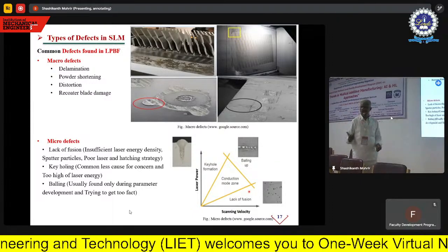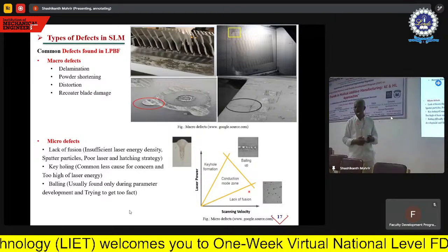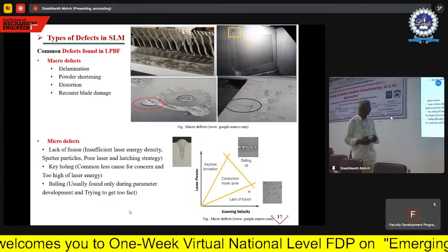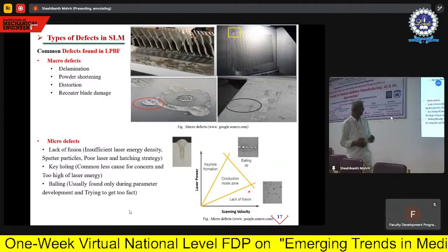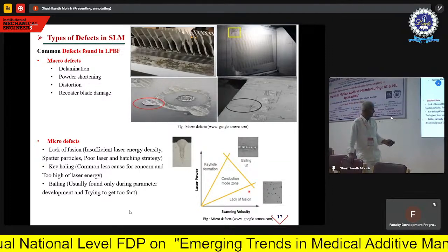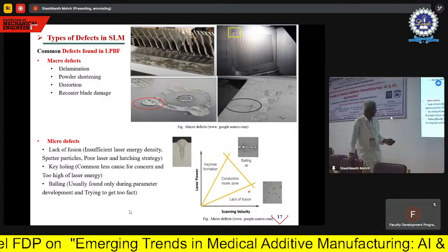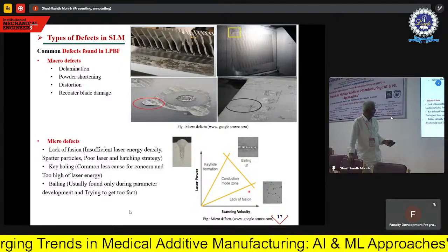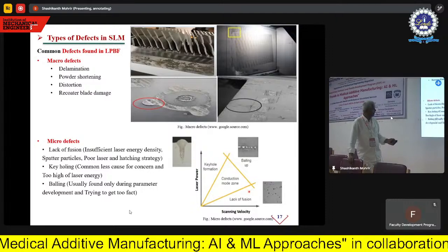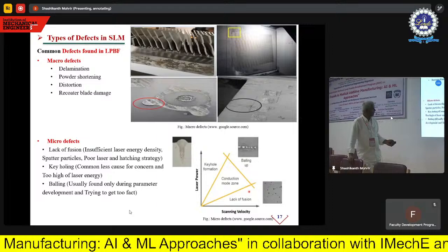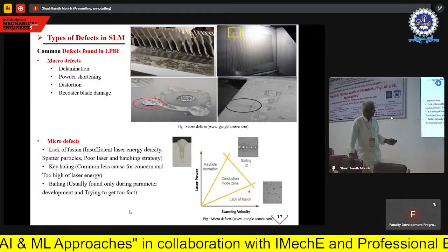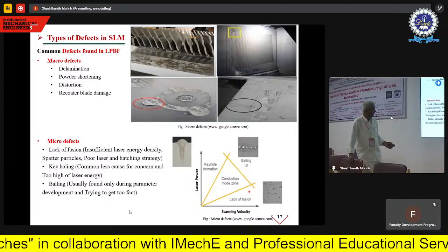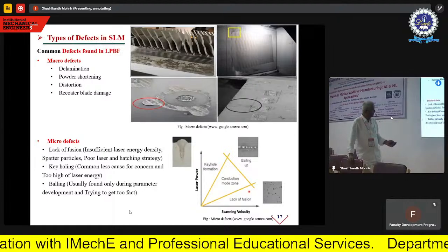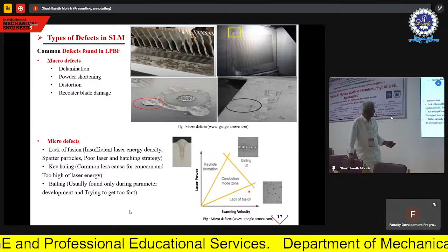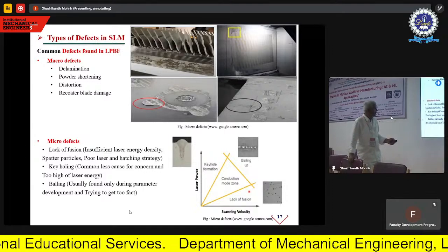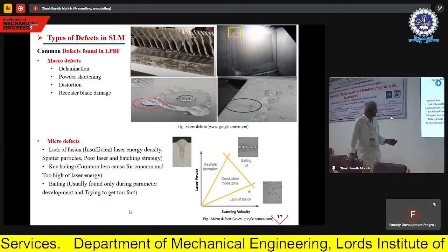So how do we achieve this fusion between the powders? Okay. So already GE was doing research in this area. So they have identified this triangle. And they told that by controlling scanning velocity and laser power for a given powder density, we can obtain a defect-free component in this zone.